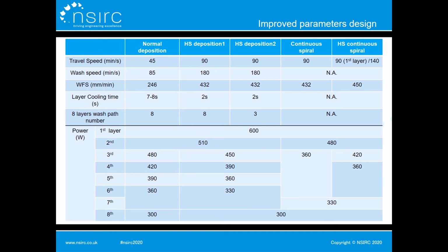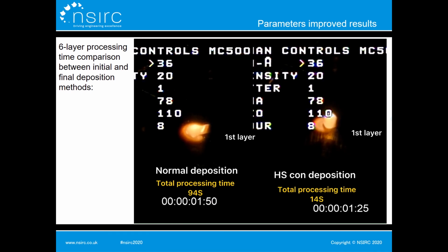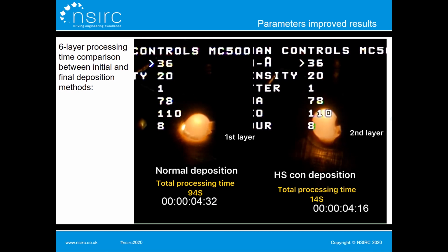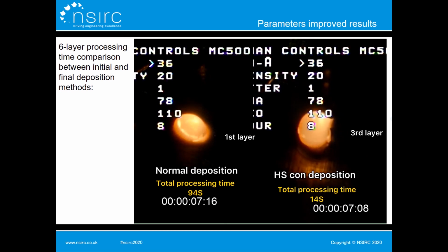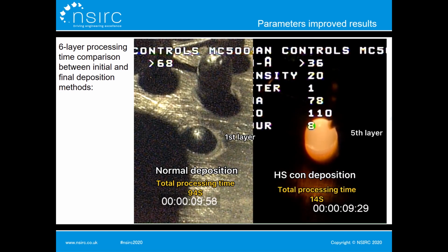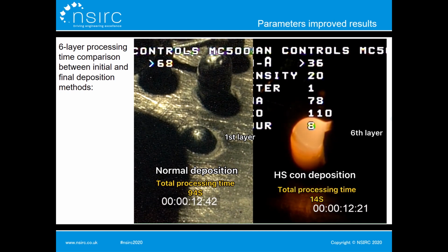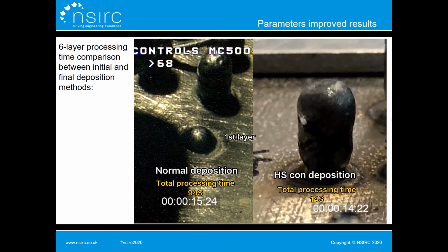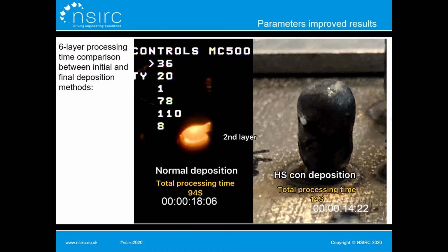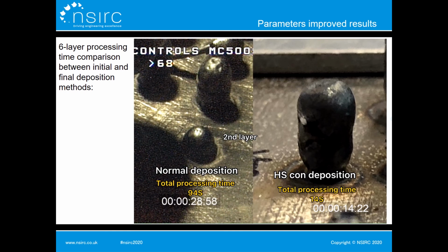The next slide is a video to show the processing difference between the initial normal deposition and the final high-speed spiral deposition. In this video, the left is the initial normal deposition, and the right hand is the final spiral deposition. We can see that after increasing the travel speed and removing the cooling time, the whole processing time is dramatically decreased. For high-speed continuous spiral deposition, it only needs 14 seconds to build up a 6-layer deposition, but for the normal method, it still needs 94 seconds.